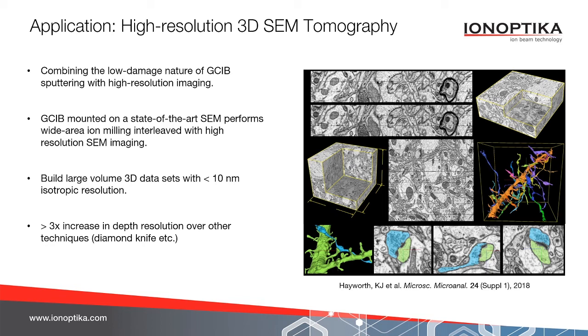Using the GCIB, they are capable of removing less than 10 nanometers per layer, combined with the very, very high resolution SEM imaging. They recombine this data to get less than 10 nanometers isotropic resolution of brain tissue. This has now been added on to the Zeiss Multisem, which is a 91 parallel beam amazing instrument. And with the GCIB, they can mill large areas of the sample and obtain 91 parallel high-resolution SEM images to do very, very high volume work.